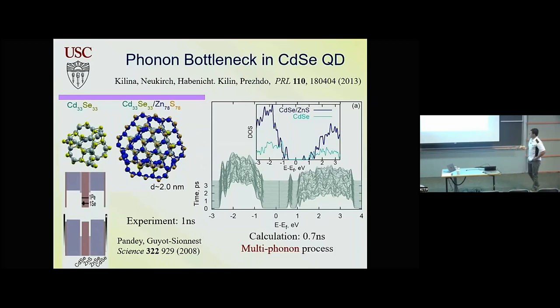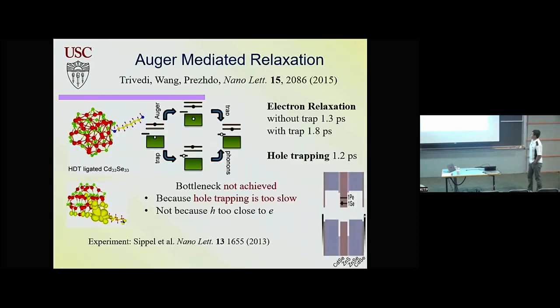And that's why when people saw this phonon bottleneck, the relaxation time that was very slow on the order of a nanosecond, they had to remove the hole, so you don't have energy exchange between electron and hole by this Auger Coulomb-like mechanism. So this is what I'm talking about. You have electron that's excited, and you have a hole. And for electron, you do see some energy gap between the lowest energy state and then the next state. In relaxation across this gap, if you have no hole, if you remove it from the core, that's what was done by Philip Guyot-Sionnest in this paper, then you can reach nanosecond relaxation.